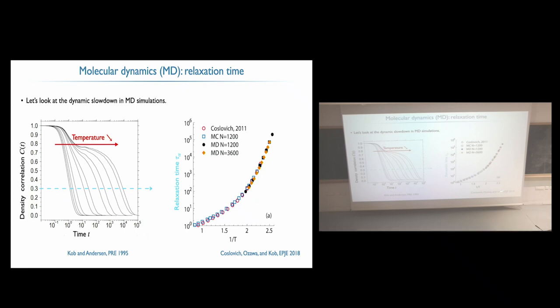So this is the state-of-the-art data. This is some simulation by Coslovich and his co-workers. This is the relaxation time, log scale again, versus 1/T. You see that this has this banana shape, so it's not a straight line. This is a fragile glass former. And you reach these time scales where the relaxation time is around 10 to the 5.